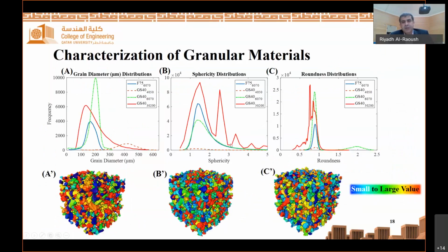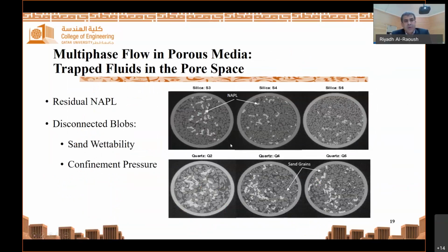These are some of the measurements that we can obtain from three-dimensional imaging in a non-destructive way. This is extremely important for our applications. So for example, figure A here shows the distribution of grain diameters in a sediment sample. And figures B and C show the distribution of important shape indices, namely the sphericity index and the roundness index. And you can see here, these are the three-dimensional images of these distributions. Everything here is done non-destructively, which is a critical factor in our research.